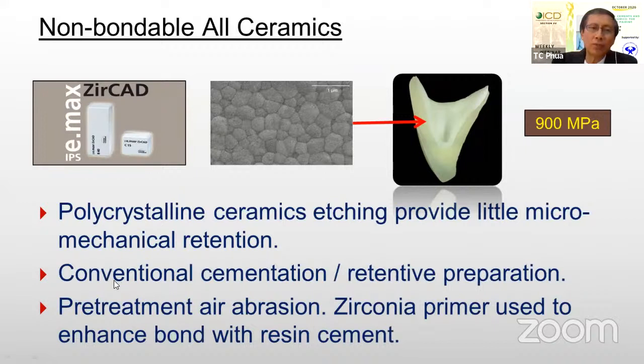You can use conventional cementation with it, but one would need retentive preparation. Remember we spoke about the 8 degree taper and the 4 millimeter crown height. And it is advisable that zirconia be pre-treated with an air abrasive type of technique, and the zirconia primer is used to enhance the bond with resin cement.